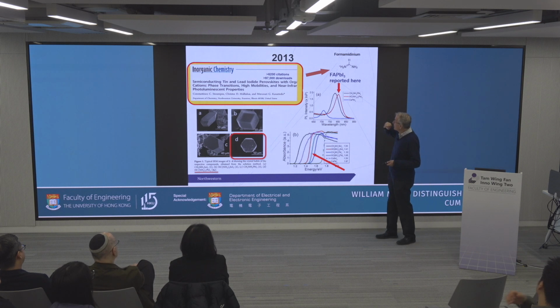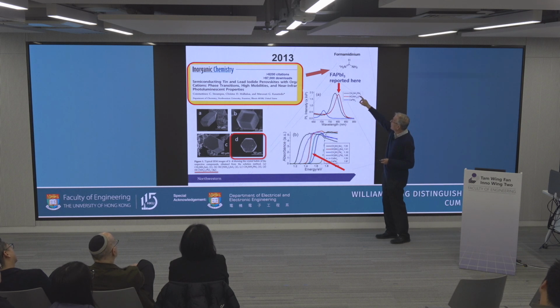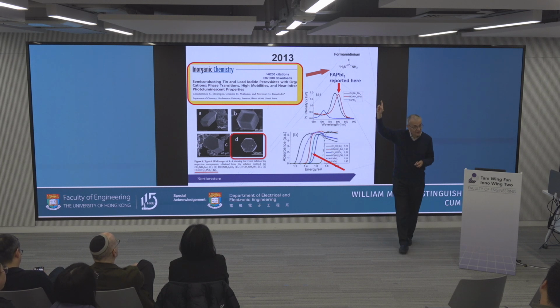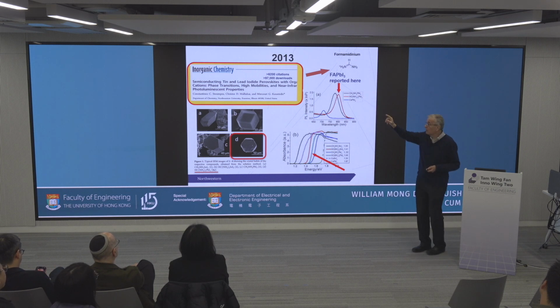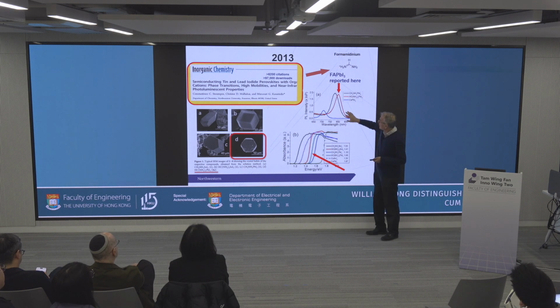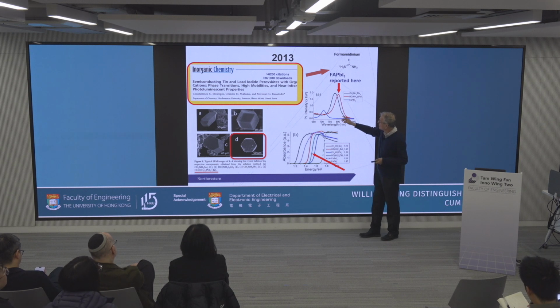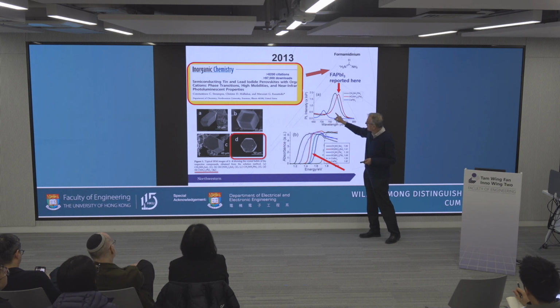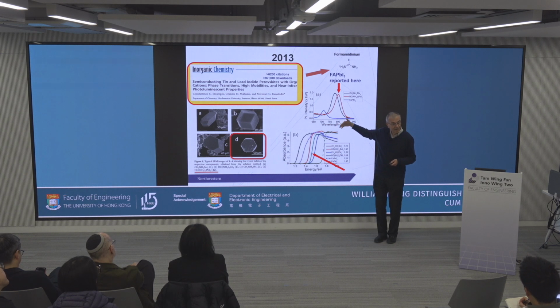And in this paper, for the first time, we published formamidinium lead iodide. This was not known at the time. It was a new compound, formamidinium lead iodide. And these are all the analogs now. All perovskite with lead, for methylammonium, formamidinium, and cesium. And you see, this is emission, and the light of formamidinium is more red, and then it's MAPI, and then this reflects the band gaps. So the band gap of formamidinium is less than MAPI.